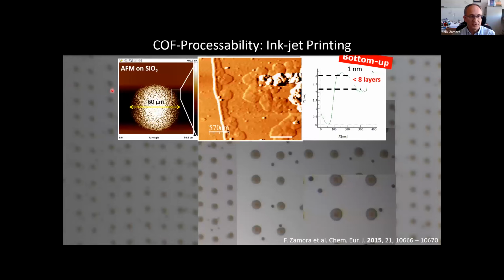And here we obtain different dots. When we characterize one of those dots with AFM, you confirm that you have a dot with a diameter of about 60 microns. And if you zoom in on this area with AFM, then you observe that the dot is composed of nanolayers of our COF with some hundred nanometers of lateral dimensions. The thickness is around 1-2 nanometers.